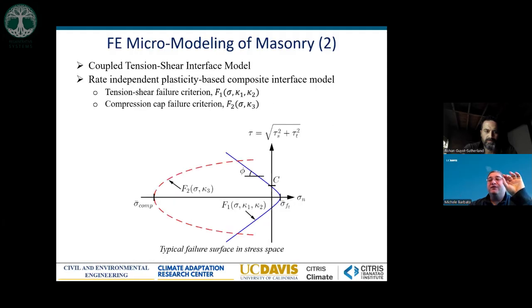So what happens? For the interface and the mortar, we needed to develop a constitutive model that is still accounting for the different mechanisms. I won't enter too much into the details of this, but fundamentally the blue line is the one that models the cracking because of tension and the cracking because of shear slipping, while the red line is the one where compression and cracking because of a combination of shear and compression is controlling the mechanism of rupture of our wall.